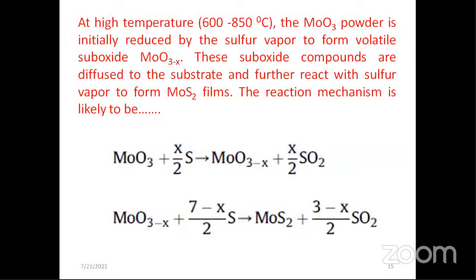This is the high temperature system we are using. The MoO3 powder is initially reduced by the sulfur. It forms a volatile suboxide, MoO3-x. After that, MoO3-x in the presence of sulfur forms the purest form of MoS2, and the other product is in gaseous form, which is removed. That is the whole reaction in my present work.